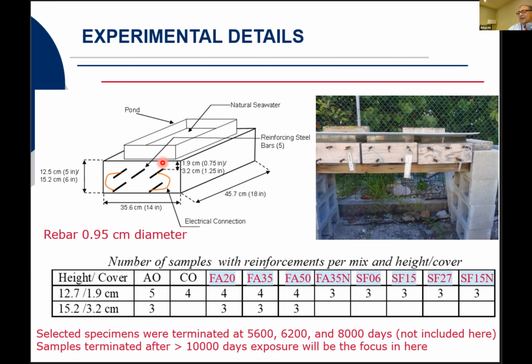And the previous effort was about 8,000 days. So from the table that you see here, we don't have all of those samples anymore, but we still have a large number. We thought it was interesting to see what the condition was after 10,000 days, and actually some of them were terminated as part of this effort.